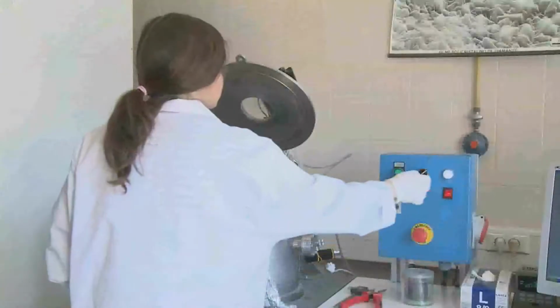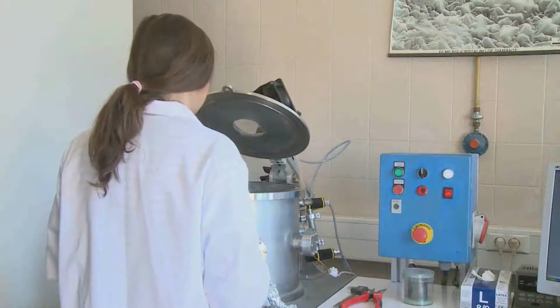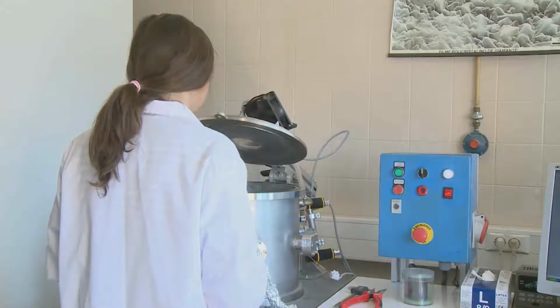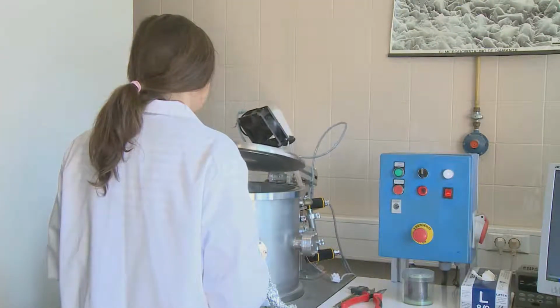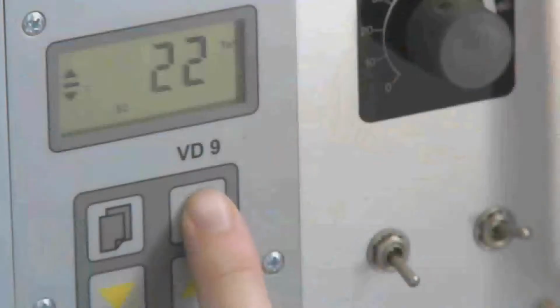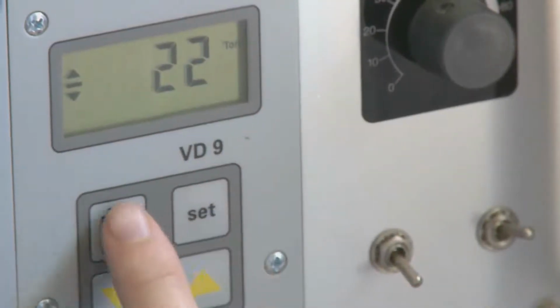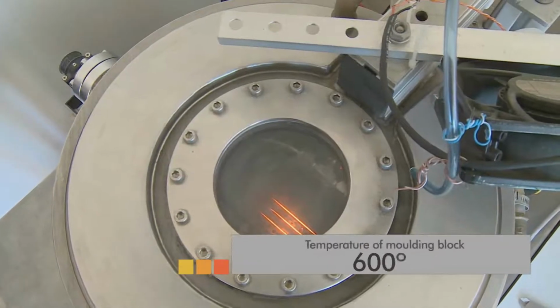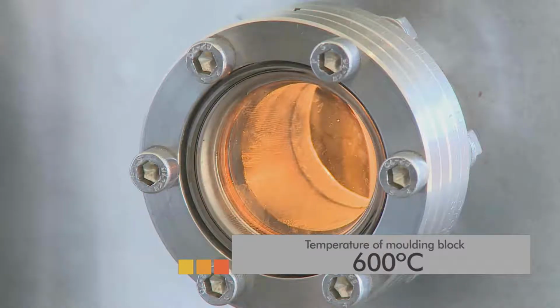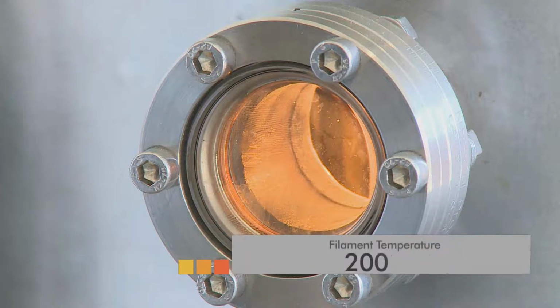The system is closed and the vacuum pump is turned on to evacuate all the atmospheric gas from the chamber. The precursor gases, in a proper balance, are turned on and the deposition pressure adjusted. At the same time, the auxiliary substrate heater is turned on. With the deposition atmosphere stabilised and the moulding block preheated, the filaments are gently powered to the deposition temperature.